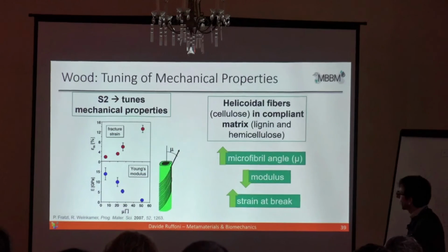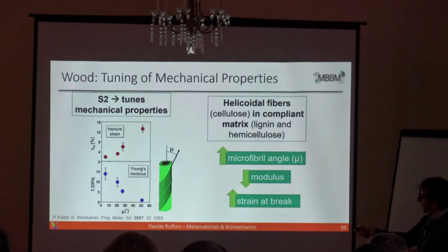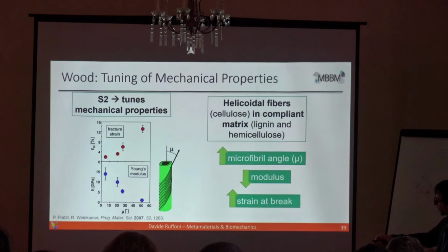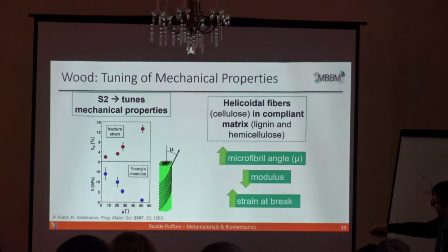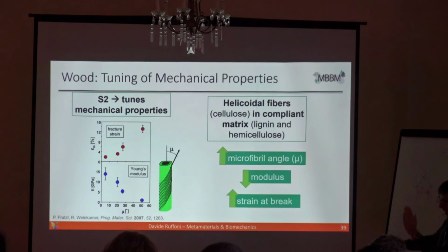And actually what we know is that thanks to the fiber arrangement in the S2 layer, wood is tuning its mechanical behavior. And the analogy is actually with an elastic spring. You can think a little bit about the wood cell wall as this elongated tube, where you have cellulose fibrils, let's say, which are wound with a spiral angle. And if this angle is small, the wood tissue is very stiff, so the Young's modulus is very high. And if the angle is increasing, this actually behaves more like an elastic spring and is more compliant.